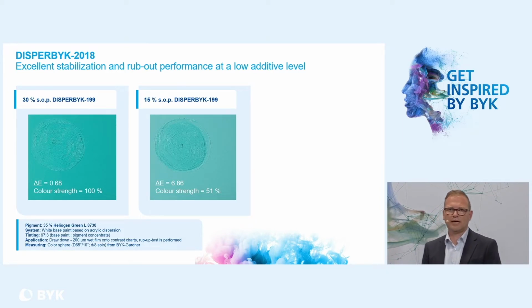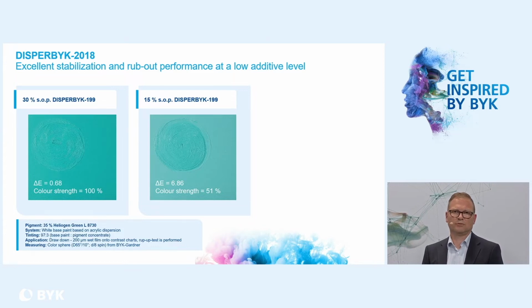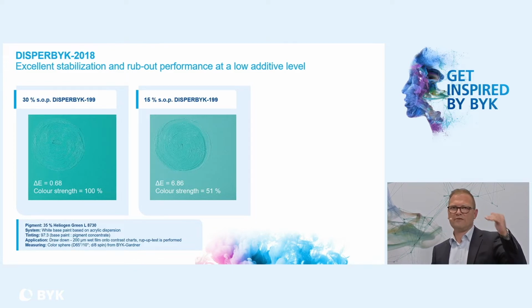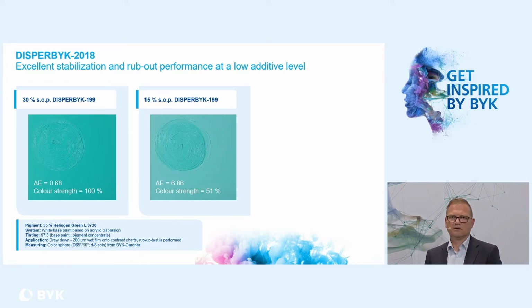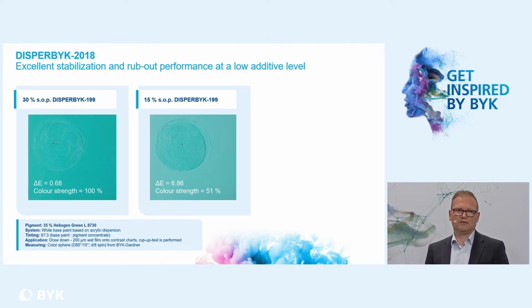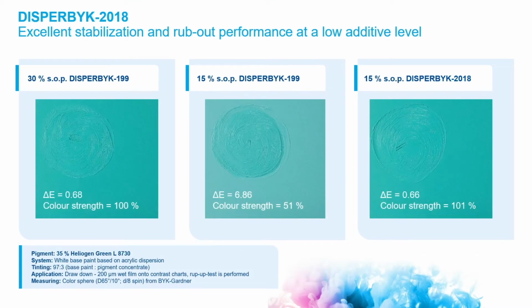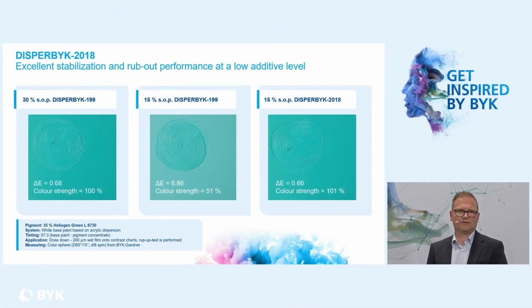And then we reduced the additive dosage down to 15% solid on pigment. And you see directly we lose color strengths and we achieve just very high delta E values. So the additive is not efficient anymore at this low dosage. But with DISPERBYK-2018 now, you see at the same low dosage, we achieved the same good high color strengths as with 30% solid on pigment of the standard wetting and dispersing additive. And again, a very good compatibility in the base paint expressed by very low delta E values. So it is more efficient and sometimes less is more. I come later to this.